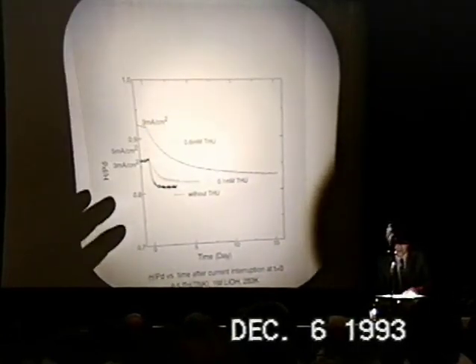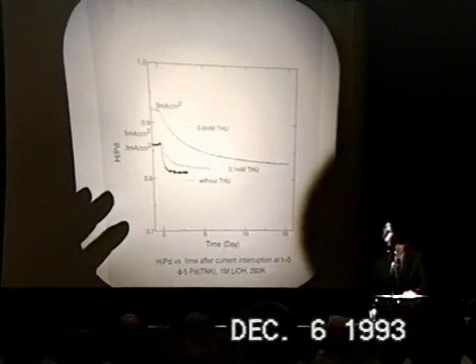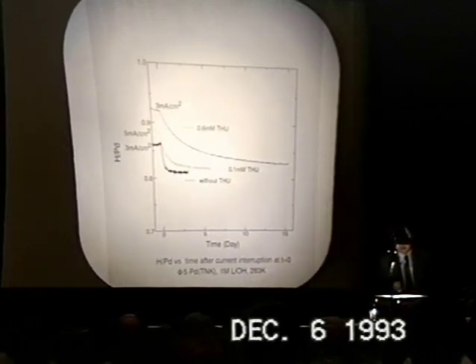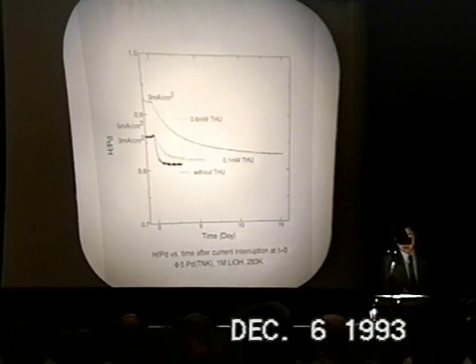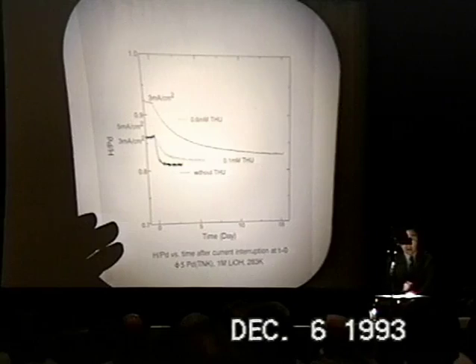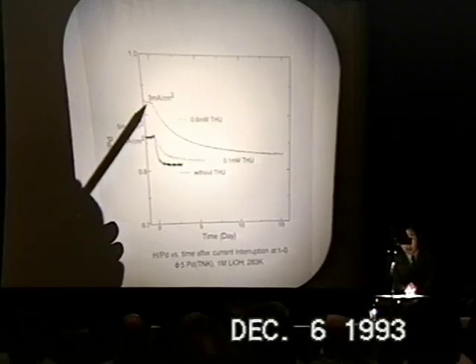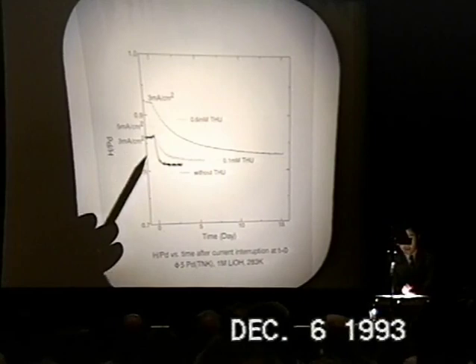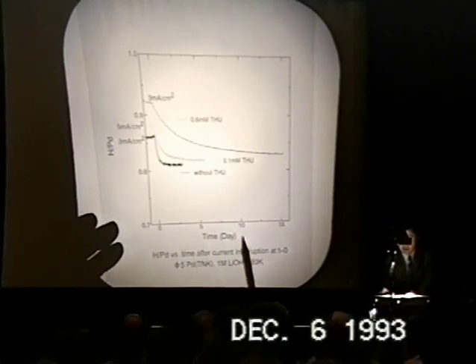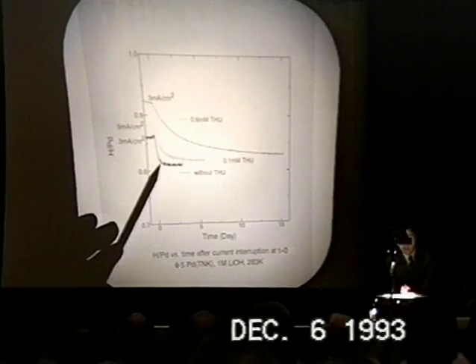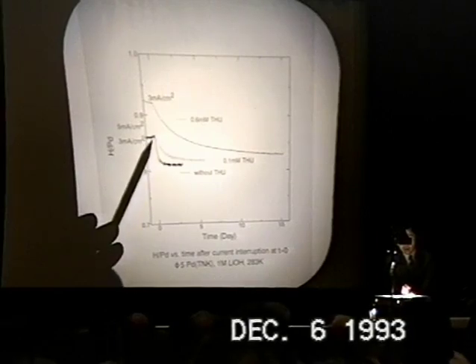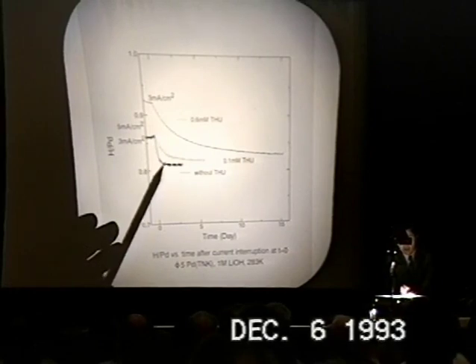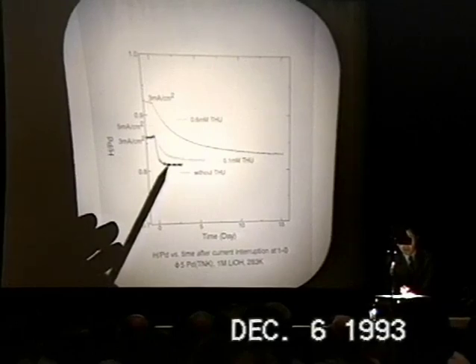And the action of thiourea is very clearly displayed by this data showing the desorption of hydrogen from the palladium cathode after the current is terminated at this time 0, as a function of time. So for pure 1 molar LiOH, the hydrogen desorbs very quickly and then reaches the bottom, and then gives rise to the hydrogen loading ratio at the equilibrium potential.